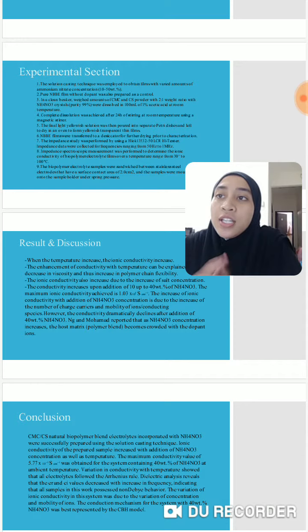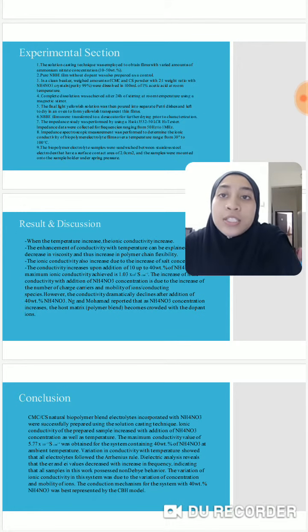Okay, so the conclusion: CMC or CS natural biopolymer blend electrolyte incorporated with ammonium nitrate was successfully prepared using the solution casting technique. The ionic conductivity of the prepared samples increased with addition of ammonium nitrate concentration as well as the temperature. The maximum conductivity value of 5.77 × 10^-5 Siemens per centimeter was obtained for the system containing 40 weight percent of ammonium nitrate at ambient temperature.